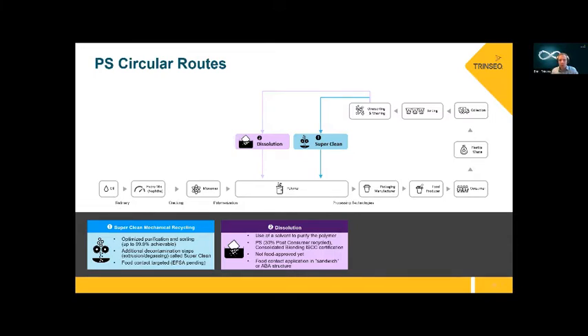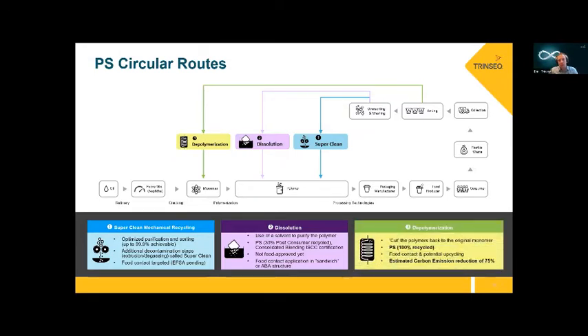The next building block, which is really appealing for polystyrene, is around depolymerization. The chemistry of polystyrene is so simple that, in fact, you need a catalyst and a little bit of heat. And then as of 350 degrees Celsius, it starts to unzip the polymer into its monomeric building blocks. That is obviously a very interesting route. You can then achieve what we call a potential upcycling. So you go from food grade down to up to food grade again. And obviously you receive a styrene monomer quality similar, if not the same, I would say the same specification as the virgin styrene monomer.